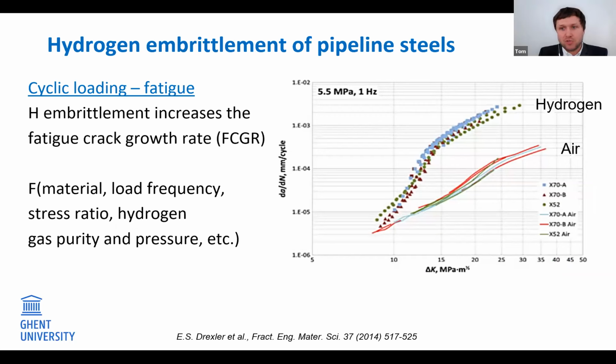Well, hydrogen-assisted fatigue crack growth takes place under cyclic loading, and this is considered to be the main mechanism of hydrogen degradation in pipeline steels transporting hydrogen gas. Hydrogen can drastically increase the fatigue crack growth rate up to 2 orders of magnitude, according to the literature. This fatigue crack growth rate test method is more appropriate for evaluation of the fatigue behavior of pipeline systems, as the method assumes a pre-existing crack. This is in line with the fact that welds, for instance, contain small imperfections, and these imperfections can serve as a crack initiation site. The exact influence is determined by many parameters, such as the material, the microstructure, the load frequency, the stress ratio, the hydrogen gas purity, and pressure. The figure, for instance, shows typical fatigue crack growth results that are obtained from fatigue testing in a gaseous environment, where you can see an increased crack growth rate in the presence of hydrogen.